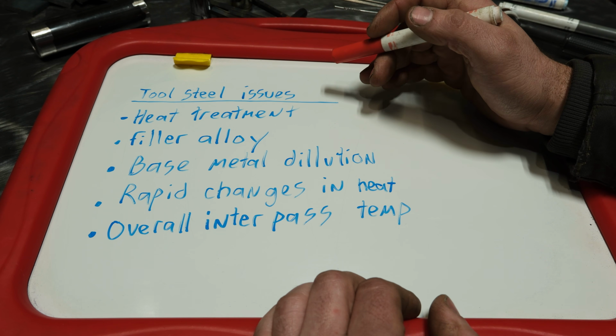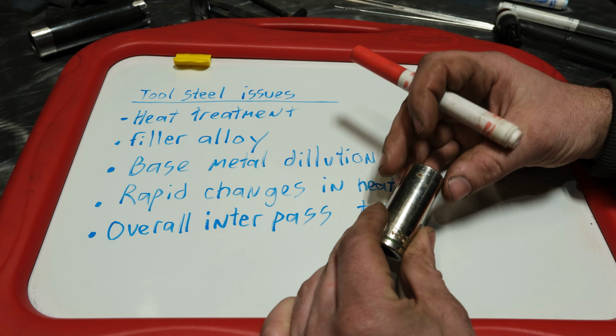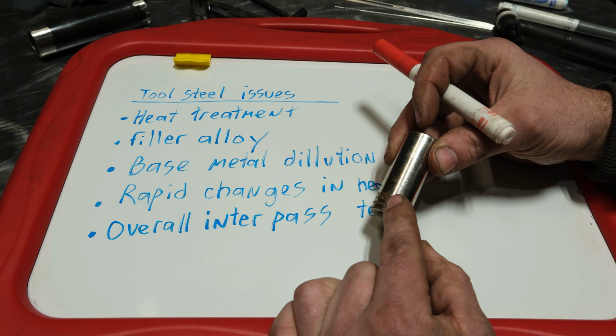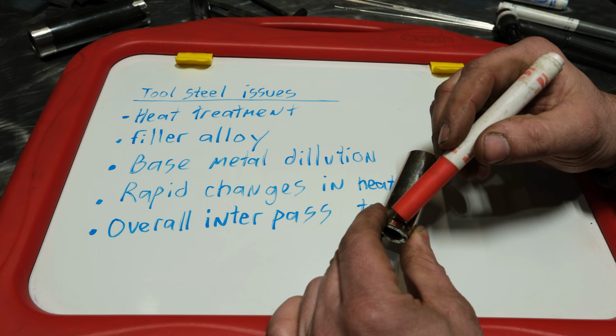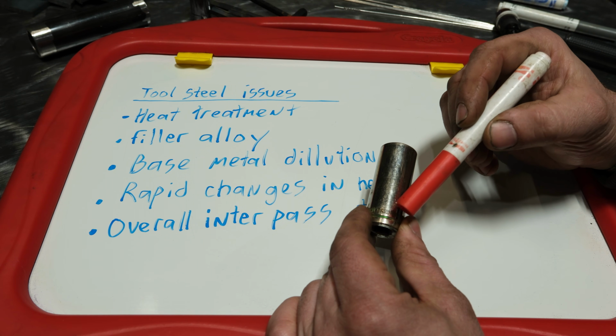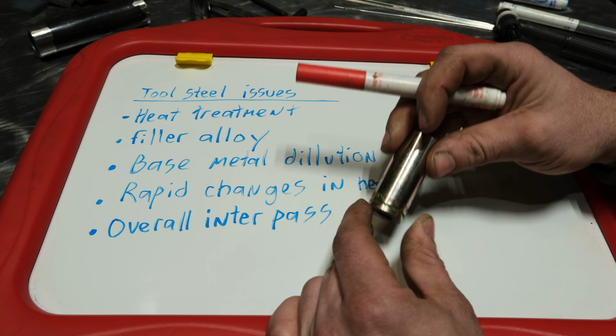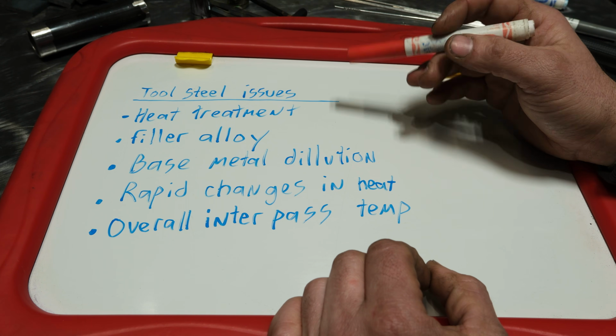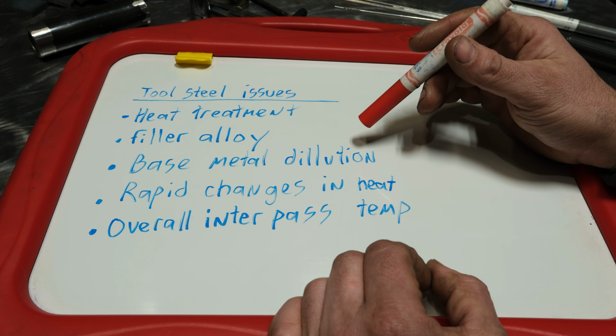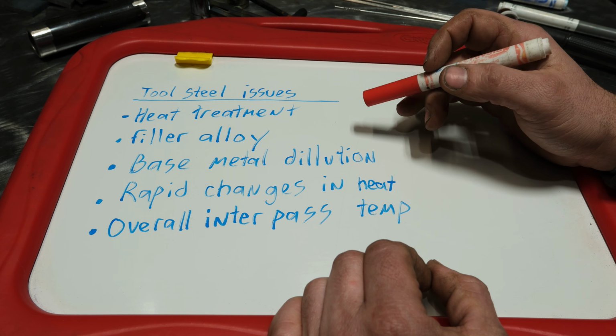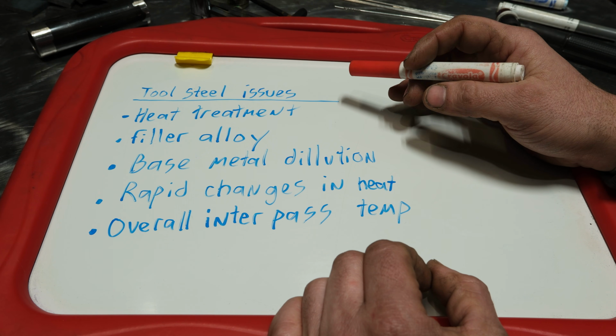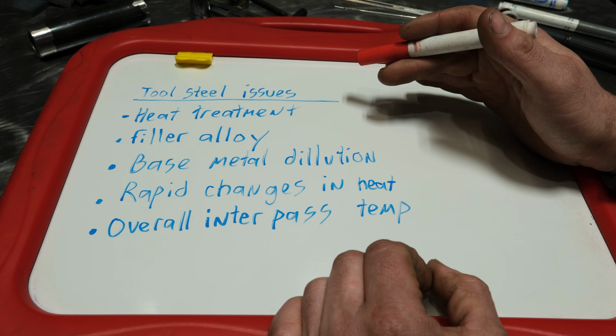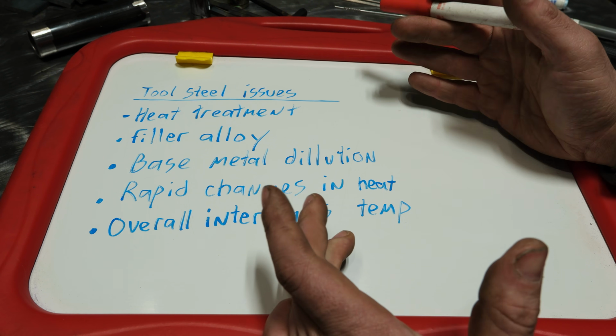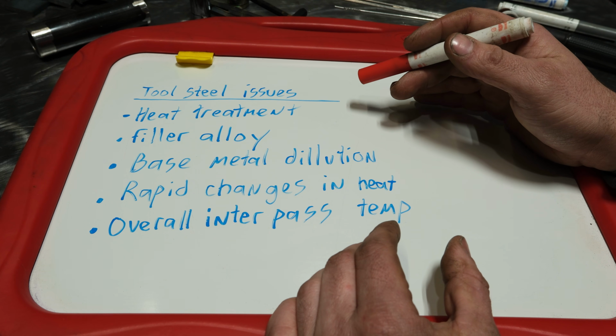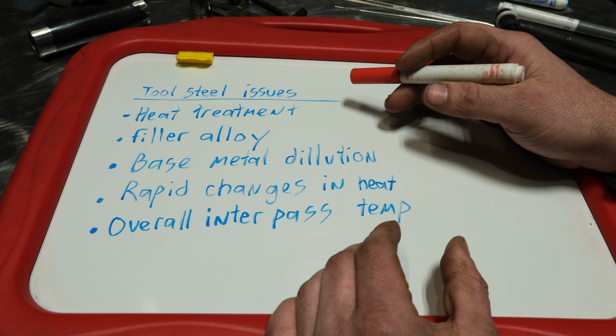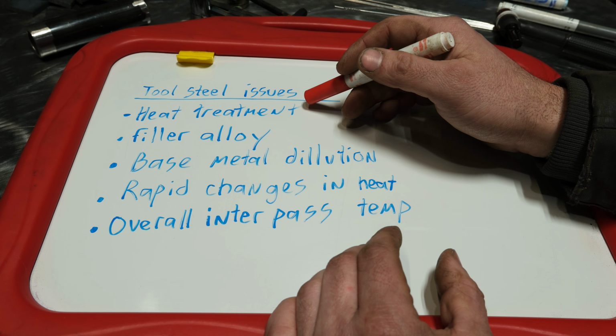Not only is it inconsistent, like when this piece here is heated throughout, the heat treatment is generally pretty consistent. Well, if you weld down on here, the heat treatment, not just in the area you welded, is now different, but likely further away from that weld is also going to be affected. And you need to understand that, because when you weld on stuff like, say, a socket or a breaker bar or whatever, you're making your own tools, you may end up with a part that is potentially more brittle than it would have been stock out of the box, or it could be softer and more likely to just spin apart, okay? And it can be very difficult to predict the results of what your weld actually did. And that is all because you are affecting the heat treatment of that part.